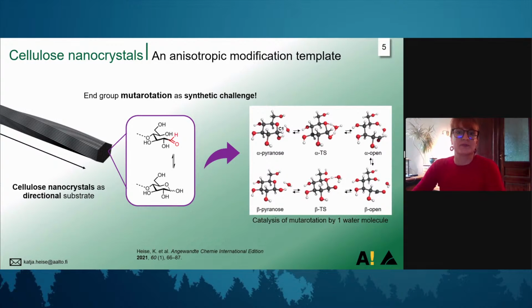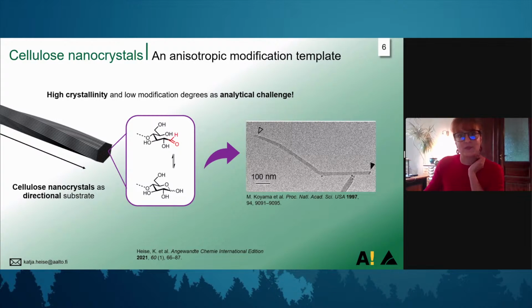For the synthetic challenges, we of course want to target aldehyde groups, but those are in equilibrium with the closed ring hemiacetal forms. And this equilibrium, called mutarotation, is largely on the side of the hemiacetal groups. So we need chemistry that is able to activate our reducing end groups, so to liberate our free aldehyde groups for the later modification. And this can be done by acid-base catalysis, or already, as shown here on the right side, by one water molecule that is catalyzing the ring opening reaction. The second challenge, and this is what I will discuss in the next minutes, is an analytical challenge.